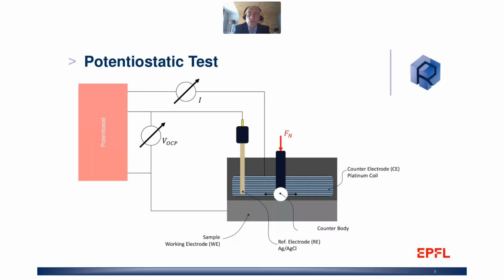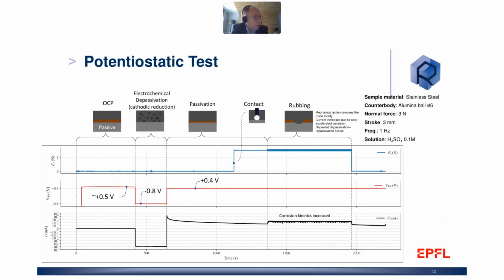The tribocorrosion cell, if you are not familiar, has the possibility, with a 3-electrode system, to have the sample as a working electrode, then a reference electrode and a counter electrode, generally platinum, in order to be able to apply a potential and then measure the current on the setup. That represents a very nice application where you could simply apply a potential. You can initially measure the open circuit potential, where you see the current under open circuit potential conditions. But by applying a potential, you can create a passivation or depassivation of the material and simply see the evolution of the current without, or before, starting a tribological test.